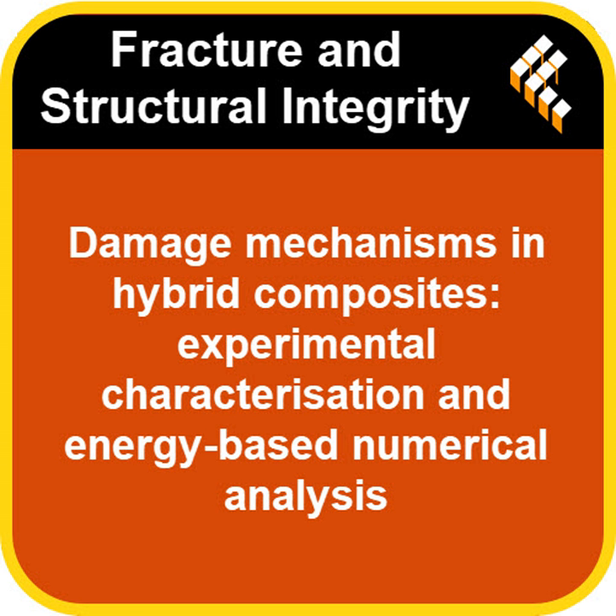Now, the big question, how did they actually tell the computer model how the material would break and fail? This sounds like the really tricky part. It is complex. They used 2 main ways to model damage. For damage within a single layer, like the epoxy cracking or individual fibers breaking, they used something called continuum damage mechanics, or CDM. Okay, CDM. They actually created their own version of this model within ABAQUS, using a special piece of code, a VUMAT subroutine. This model basically uses a limit on how much stress a fiber can take before it breaks. A failure criterion. Exactly, a maximum stress failure criterion.